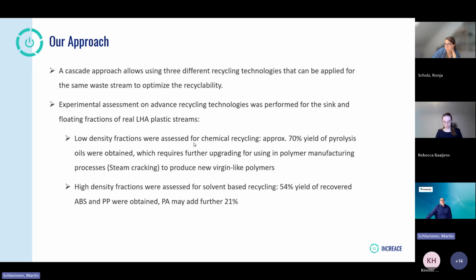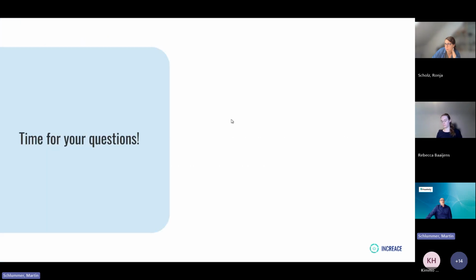The low density fractions were assessed in chemical recycling and showed a 70% yield of pyrolysis oils, which for sure require further upgrading and steam cracking. And for the high density fractions, as I said, a 54% yield of ABS and PP, and probably another 21% from polyamide. So this is just to suggest how this could all work together, and probably a good time to start any questions.